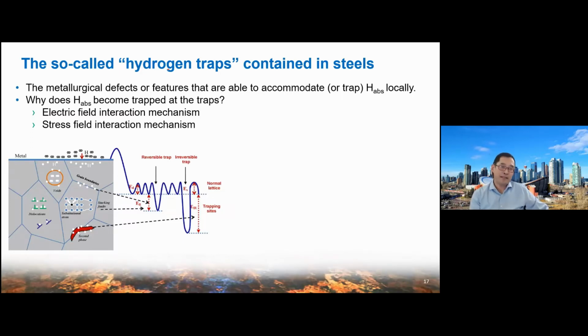Basically, there are two mechanisms. I will very briefly introduce them. The first one we call the electrical field interaction mechanism. Hydrogen can neutralize the local electricity at these defects to make the charge balanced. This is a driving force for hydrogen to become locally trapped.